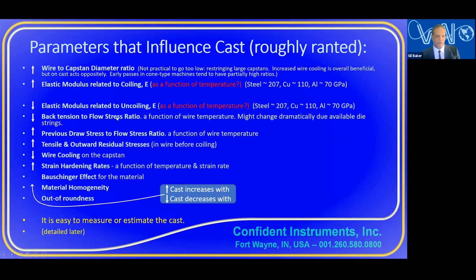Back tension, of course, I mentioned before, is really straightening your wire back again. So how high that is is going to be important. You're going to have more cast when you have a lower back tension. Then the previous draw stress to flow stress ratio. For coiling, the draw stress is going to cause yielding in the wire. And similarly, when you are uncoiling, the flow stress and the back stress, oh, that's up here. Okay, so these two are up here.